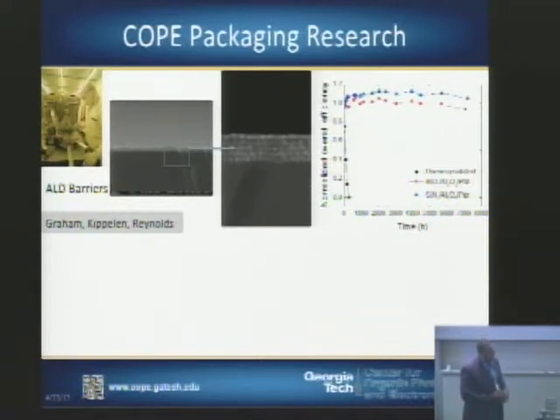Some of the other aspects that we're looking at in terms of the reliability and the packaging of organic photovoltaics and other organic electronic devices is through the creation of ultra barrier films. It's widely known that a lot of these materials are susceptible to exposure to the environment. And so we've utilized recently a lot of atomic layer deposition to create oxide barriers. Some of these oxide barriers are monolithic films. Some of them contain a number of different layers, so we're mixing materials together in order to create ultra barriers where we can package devices, which we've demonstrated in the past, that show very little change in the overall power conversion efficiency over the period of several months. And so this is a shelf lifetime analysis.